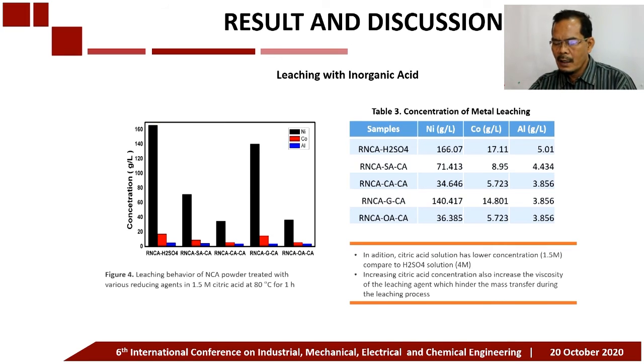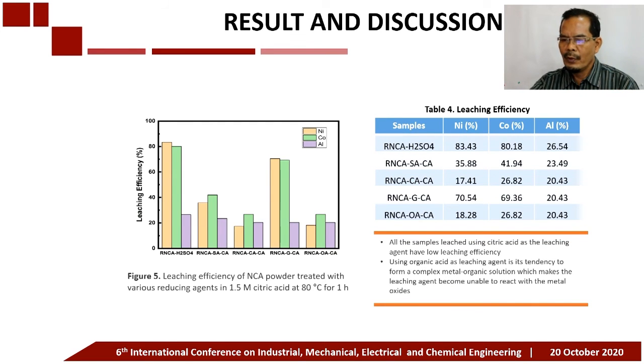From here we can say that the citric acid solution has a lower concentration. And increasing citric acid concentration also increases the viscosity of the leaching agent, which hinders the mass transfer during the leaching process. In terms of efficiency, the best leaching efficiency using citric acid as a leaching agent was only around 70%, in comparison with sulfuric acid at around 83%. This shows that sulfuric acid is more effective as a leaching agent.